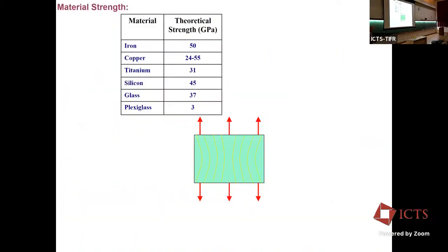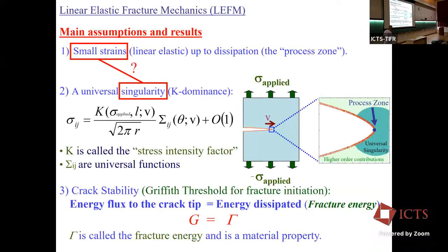Okay. So when you first tried the experiment, I assume already there will be minute cracks in the material. Why didn't they initiate a propagation? Okay, great question. We go backwards again. Because this coefficient of the singularity depends on the length of the crack. So if it's very small, the coefficient becomes small. And even though you have a singularity, you don't have enough energy to actually break bonds.